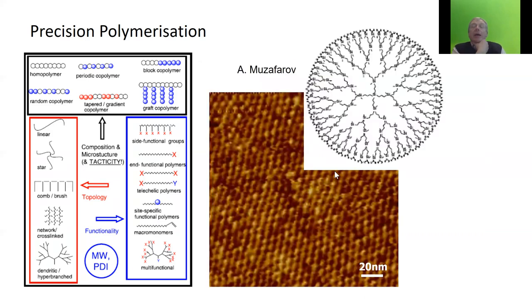But I come back to very defined molecules, and I want to come back to the dendrimers, and I show this example of a carbosilane dendrimer, very large, very well defined, and each molecule forms a sphere which has exactly the same size. So it's not only a molecule, it forms a defined sphere of a defined size. And that was achieved by synthesis, in this case by Aziz Muzafarov here in Moscow.